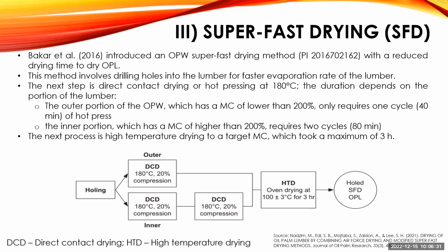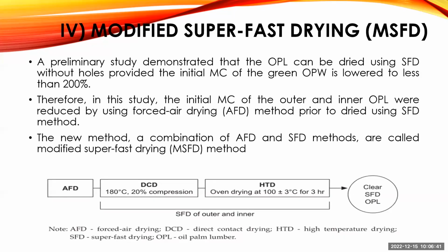This means that during the lamination process, you can see there is a hole on the surface of the oil palm lumber. Therefore, I would suggest using the modified superfast drying method instead.